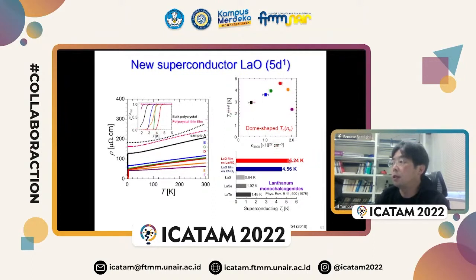And this superconducting transition temperature is much higher than lanthanum monochalcogenides. Lanthanum telluride is 1.4 Kelvin, lanthanum selenide 1.0 Kelvin, and lanthanum monosulfide 0.8 Kelvin. So this is a chemical trend. From this chemical trend, lanthanum monoxide should show the lowest superconducting transition temperature, but this lanthanum oxide thin film shows the highest superconducting transition temperature. This is some irregular chemical trend.